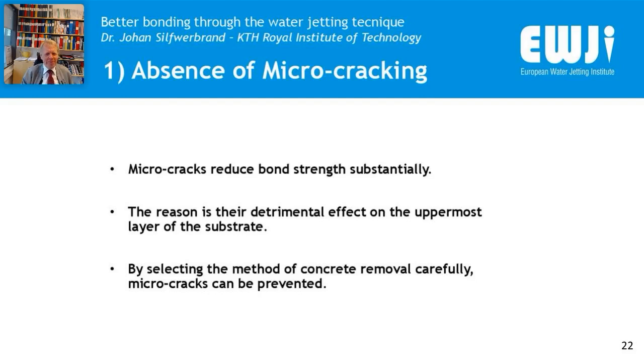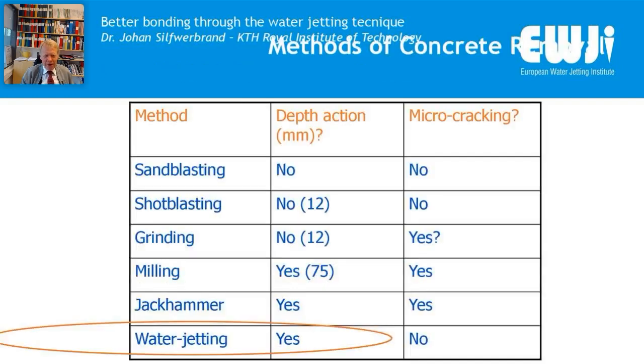And you can guess that water-jet technology is among these methods. So here you can see some methods that are used for repair and improving the surface. On top you have sandblasting and shot blasting. And of course, they are quite good in cleaning the surface, and they are not causing microcracking, but they do not have any depth action. So if you need to remove some centimeters of concrete, they are not a realistic alternative.